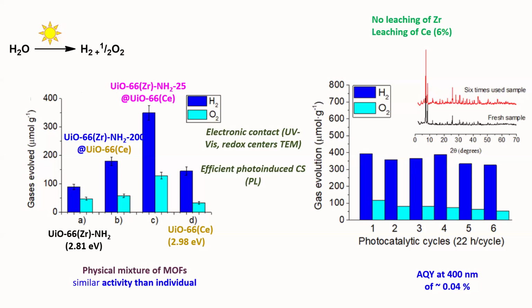And obviously we wanted to check the stability of the solid, because people always say that upon irradiation MOF is not stable, so it loses its structural stability. But we wanted to make sure, so the solid was reused for 6 cycles, and each cycle corresponds to 22 hours. So we have shown that the solid exhibits more or less identical activity for the generation of hydrogen as well as oxygen.